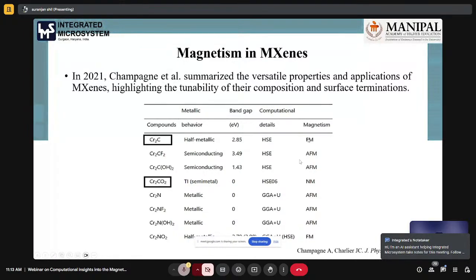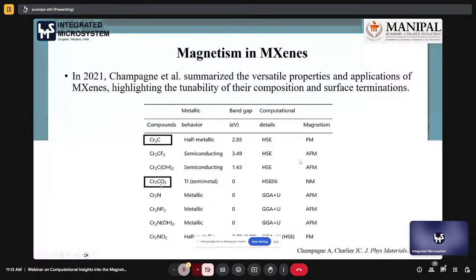got it ferromagnetic. But when they terminate this with the fluoride, they got semiconducting behavior with band gap 3.49, and they got it antiferromagnetic. When they terminate with the hydroxyl group, they got antiferromagnetic. But in chromium carbide with oxygen termination, they got non-magnetic, but nitride they got antiferromagnetic. Again, for chromium nitride and oxygen termination, they got ferromagnetic.